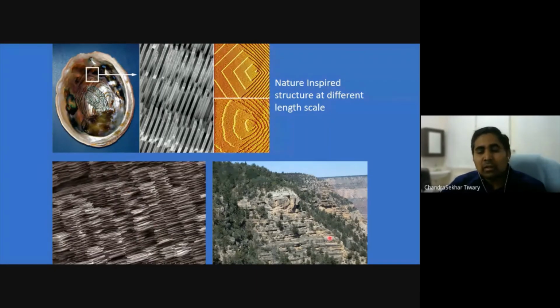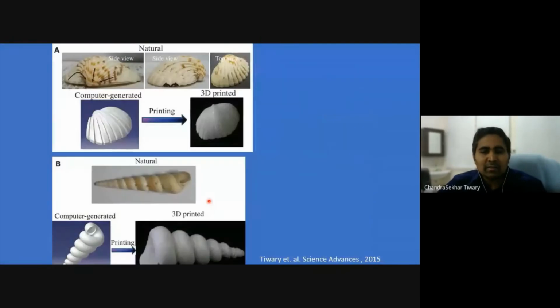But if you go around in mountains and so on, you do see a similarity. And remember, these are meters thick. You do see a ceramic layer of deposition separated by organics in between. And that also gives it stability. And these structures are stable for ages. In some places you can see, although there is erosion, they can still take the load, or the structure can be stable. So the idea is, if you have something at nanoscopic or even microscopic level, the mechanics does have a role to play.